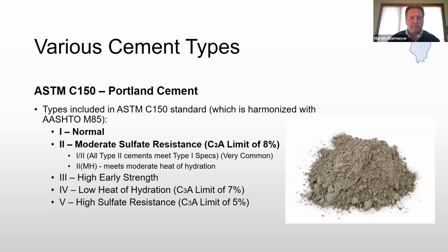Also, there's a note here, it says type 2 MH, which meets moderate heat of hydration. Heat of hydration is important when we do mass pours. Any geometrical area whose smallest dimension is more than 3 feet can constitute a mass pour, where we have to watch our heat of hydration and the heat differences in a slab.